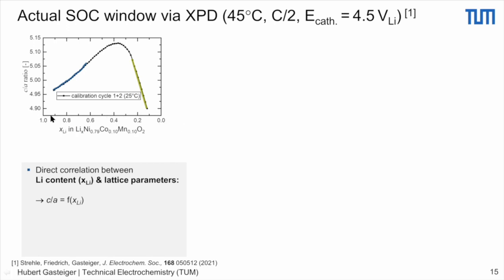So this is in the fully discharged state, this is in the fully charged state. And what we find is this sort of calibration curve of C over A. And from the C over A calibration, we can get the amount of lithium which is in the material. Of course, you could do the same thing by, let's say, ICP analysis. And so these are the two regimes, in the discharged electrodes and then the charged electrodes, you can get the relationship between the C over A parameter and the lithium content. And what we see is when we cycle the cells from beginning of test to end of test over 700 cycles, in both the charged state and the discharged state, we are narrowing the SOC window.